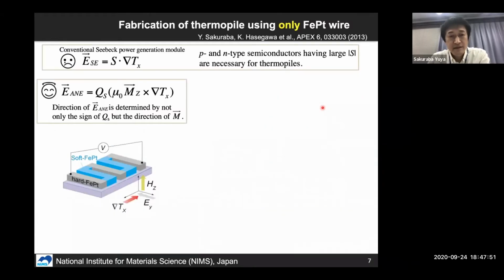And another interesting advantage of anomalous Nernst effect is that we can fabricate a thermopile structure using only one magnetic material. As I mentioned, in the Seebeck module, the direction of the Seebeck electric field depends only on the sign of the Seebeck coefficient, so it is usually necessary to use P and N-type semiconductors to form the thermoelectric module. However, in the case of anomalous Nernst effect, the direction of the anomalous Nernst effect electric field can be controlled by the direction of magnetization in the ferromagnetic material. So we don't need to use two magnetic materials having the opposite sign of QS.